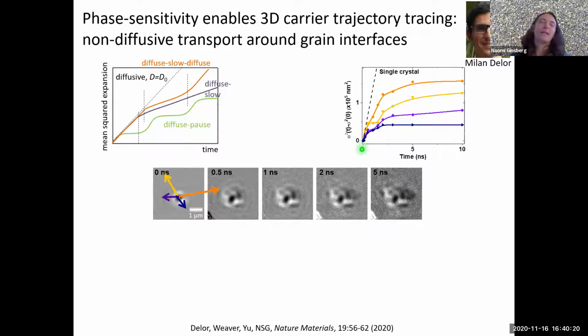So what we think is happening is that initially you just have free diffusion within one crystalline domain, but then encountering an interface pauses the lateral transport, and that's when we see these brighter contrast spots show up. But then at a certain point, these carriers find a way across the interface deeper into the film, and then they can continue to diffuse again. And that happens until essentially they all get trapped. And in this case, the lifetime of these carriers is about an order of magnitude larger than this. It didn't seem very exciting to keep on going, but this is also a way to be able to measure the fact that there are deep traps in these materials.